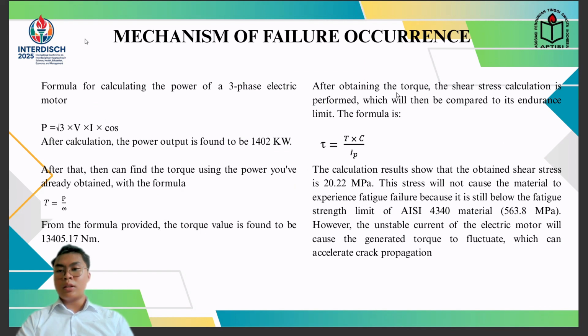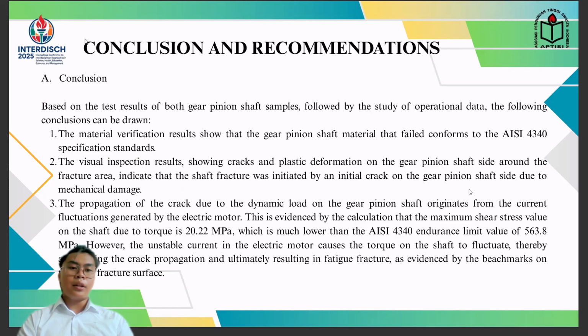After obtaining the torque, the shear stress calculation is performed, which will then be compared to the endurance limit, and this is the formula for shear stress. The obtained shear stress is 20.22 MPa. This stress will not cause the material to experience fatigue failure because it still belongs within the fatigue strength limit of AISI 4340 material. However, the unstable current of the electric motor will cause the generated torque to fluctuate, which can accelerate crack propagation. And this is the conclusion.